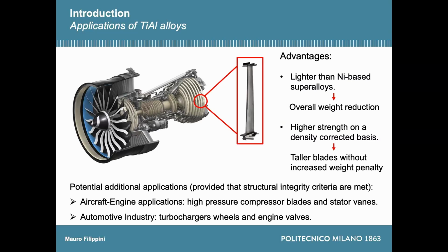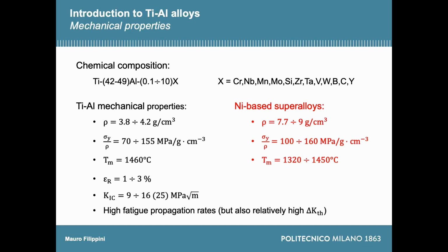There are new potential applications, but there is still debate about that. Again, in aero engines for high pressure compressor blades, but there is a limitation on that. And in the automotive industry for turbochargers and engine valves, mainly for motorsport nowadays, no longer for conventional cars. So the chemical composition is more or less a balance, in atomic percentage, between titanium and aluminum, and then you have additional elements to promote different properties like corrosion or oxidation properties. This is the reason to introduce niobium and chromium, for instance.